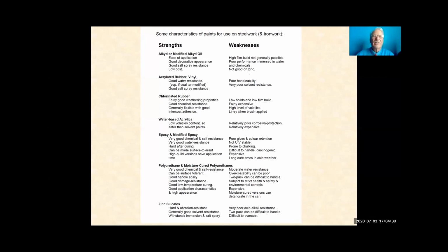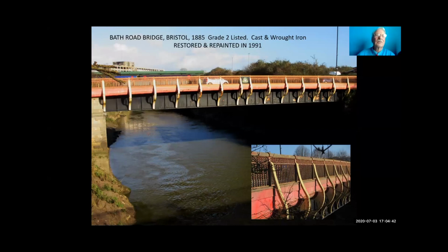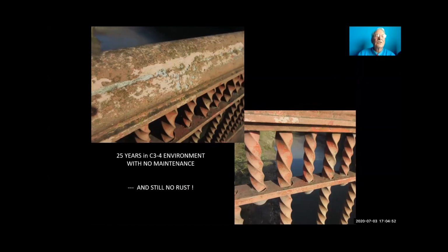This is what an epoxy and polyurethane two-pack system looks like after 25 years. I have personal experience with this one. You can see that in this C3, C4 environment, it's actually still doing its work. It's keeping the metal from rusting. The top coat has pulled off because in this area where it dips down in, when the sun comes out and the paint expands, and then the sun goes in and it gets cold, the paint contracts, the cycles tend to make it come unstuck from the surface. So the top coat and indeed the filling coat here, the intermediate coat, have parted, but the primer has stayed on. You can see here the top coat is finished and it's fallen off as well.